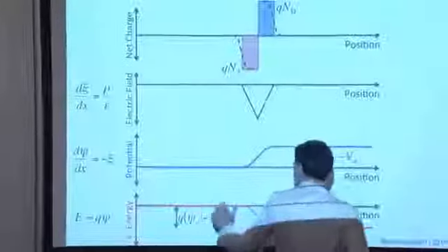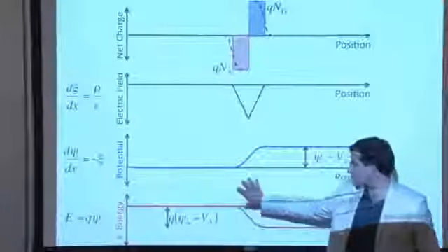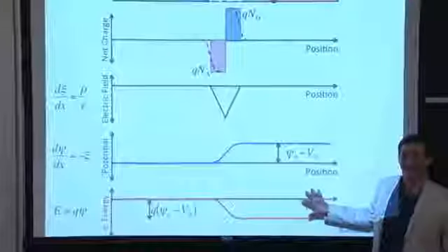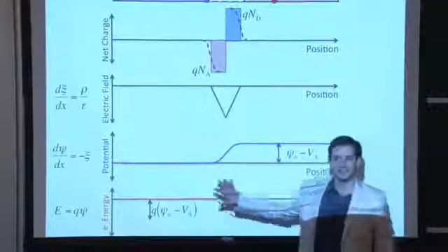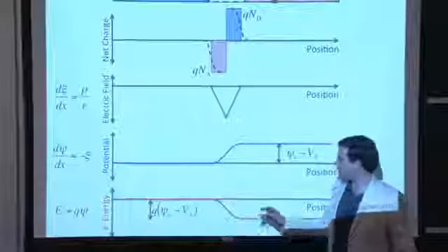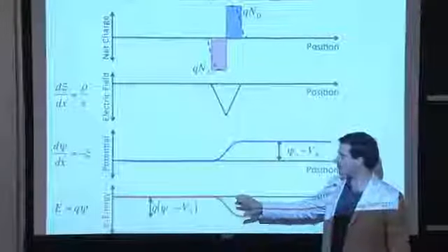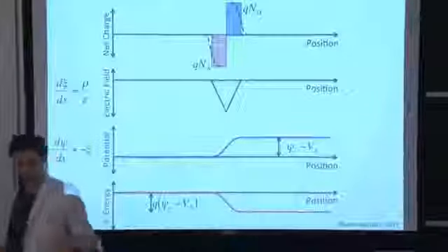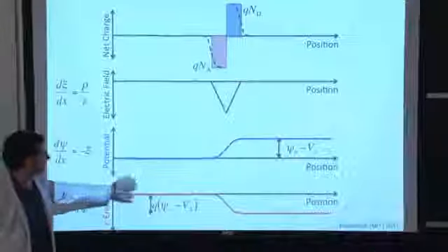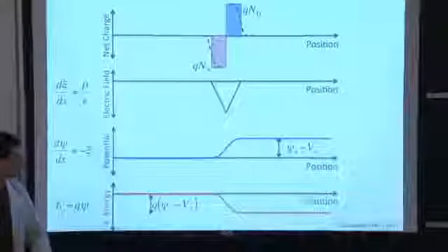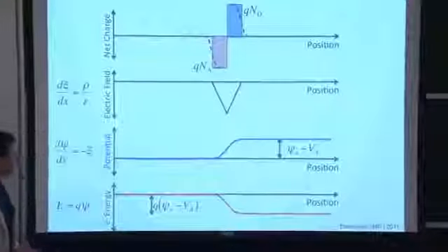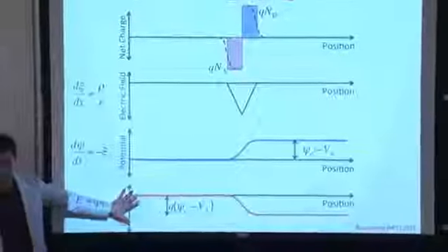Obviously, if you give them an opportunity, all the electrons would want to come down to this side. But why wouldn't all of them come down over here? Because of diffusion, right? So there's that balance of the two effects. There is a net energy gain for the electrons, but diffusion is what's driving some of the electrons back across the other side of the junction. It's that equilibrium which is establishing the final energy band diagram of the p-n junction, which is really looking something very much like that.